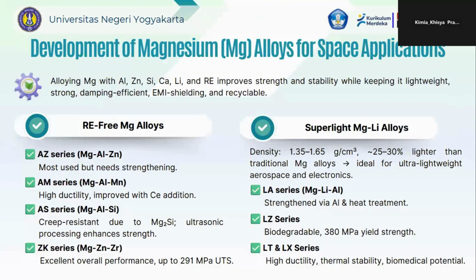Next, to improve the performance of magnesium alloys, researchers have alloyed magnesium with elements like aluminum, zinc, silicon, calcium, lithium, and rare earths. This alloying improves mechanical strength, corrosion resistance, and thermal stability while keeping the material lightweight, recyclable, and efficient for EMI shielding. For rare earth free material with magnesium alloy, it will be AZ series or magnesium, aluminum, and zinc, AM series, AS series, and ZK series,